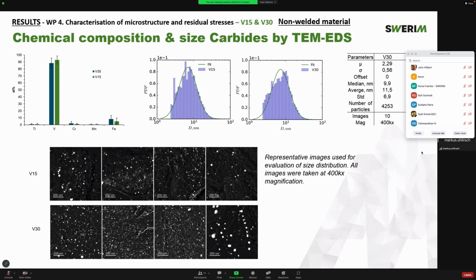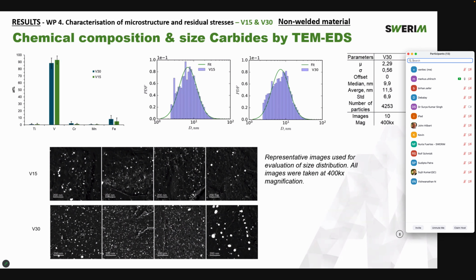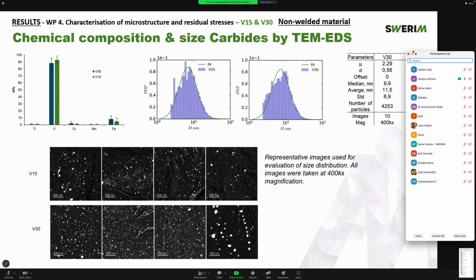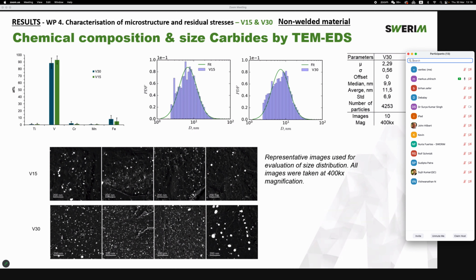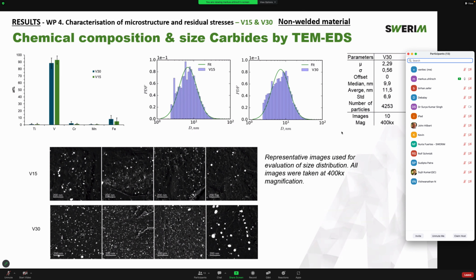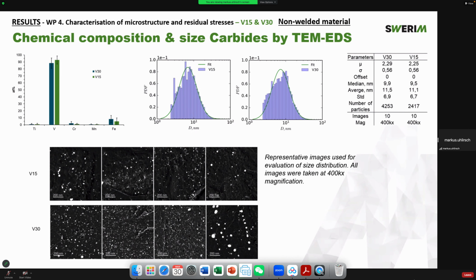Here we see the chemical composition of the carbides in the graph on the top left. Even though the bars are slightly different for V15, the 0.15% vanadium, and V30, the 0.30% vanadium material, we cannot finally say that one has more or less vanadium than the other, since it cannot be measured that precisely. It could be that there are small changes in the stoichiometry, but it's hard to prove because even the APT technique cannot differentiate so well between those two.